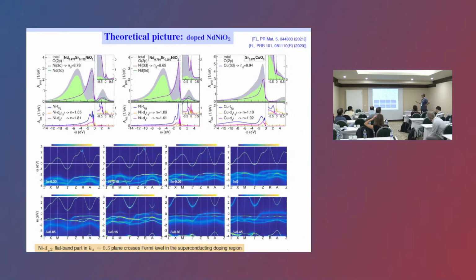And if you look at the orbital sector, we still see, as Carsten and others put forward, that even in the overdoped region it's mainly single orbital. So this orange-like thing that you can hopefully see here is the copper x-squared minus y-squared at large doping, and that is the only orbital that is important. Whereas for the same kind of doping in the nickelate, it's quite different. The holes go here into this nickel d z-squared because that is energetically much more favorable than putting holes into the x-squared minus y-squared when you have this more Hubbard picture.